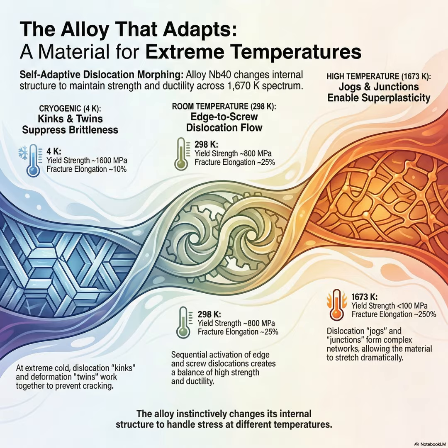And what they saw was this beautiful sequential activation. The initial stretching, the first bit of plastic flow, is dominated by what are called edge dislocations. And those are different from the screw dislocations. Yeah, you can think of the edge dislocations as the fast, highly mobile frontline workers. They move quickly and relax the initial local stress.